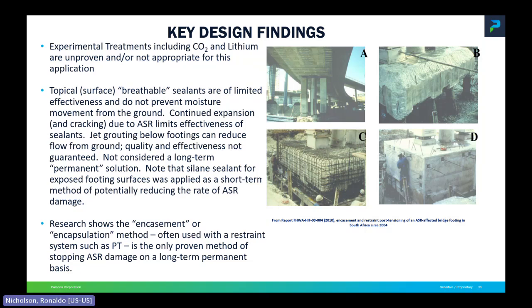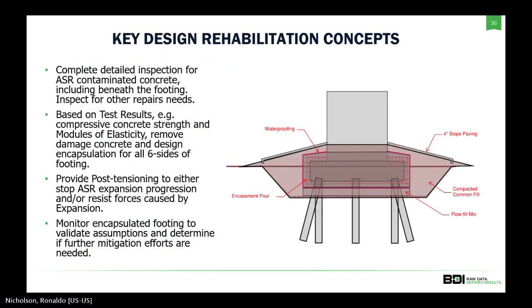So based upon the previous study, we turned to an encasement or encapsulation method, where basically we would restrain such expansion due to ASR by confining the core load path within the footing. This is an example that was done in South Africa on a similar footing, where you see both the mat and the post-tension footing as an end result. So our conceptual concept was to do something similar.